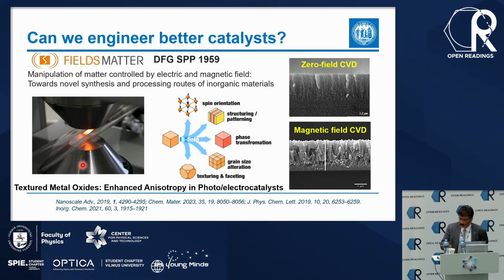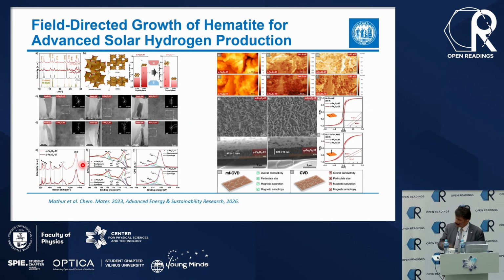And we have worked on this for almost 8 years now. We have learned that a magnetic field, which has very little energy, can change the spin orientation on the surface. It can change the texture, what facets are exposed. It can help in phase transformation, texturing, and faceting. And we did this for iron oxide. It's a detailed study. It has appeared in Advanced Energy and Sustainability Research.